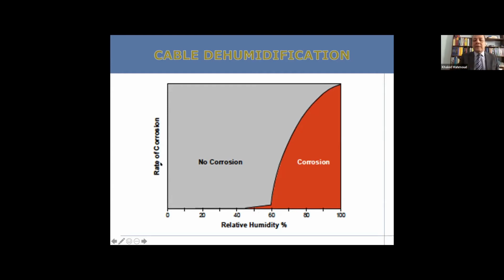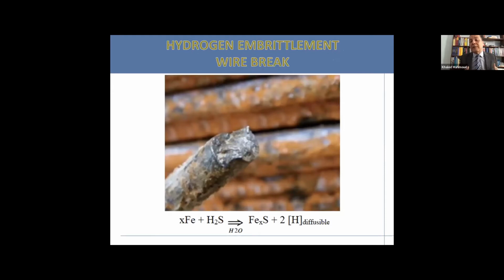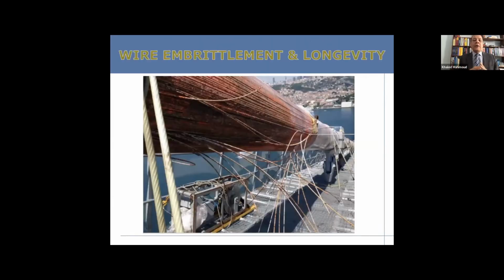What matters at the end of the day is how much hydrogen will be contained in the bridge cable environment. And if you look at the metrics of bridge wire degradation, in our view, it is broken wires and cracked wires. If we have less of those, that's a good sign. That's a positive sign for the bridge cable. If not, then there is something to contemplate and something to study there. So in all, you don't want to have this kind of image when you open your bridge cables in a few years, regardless of how old the cable is. Is it 30 years, 50 years, 80 years? Whenever, the first opening of a cable should not look like this, which is a total disaster.